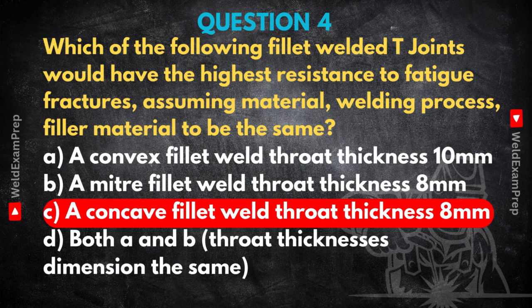Precisely. Now compare that to the concave fillet weld, option C. Its profile curves inwards, creating a much smoother, more gradual transition at the weld toe. More like a gentle ramp than a sharp corner. Exactly. That smooth profile distributes the stress much more evenly, reducing that peak concentration right at the toe. This makes it significantly more resistant to fatigue cracks starting, even if the nominal throat thickness is slightly less, like the 8 millimeter here compared to the 10 millimeter convex one.